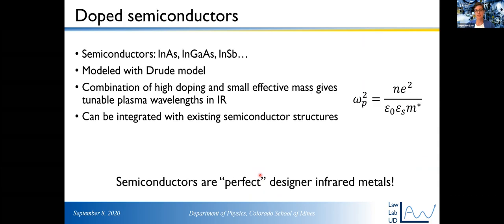So the materials that we're interested in are doped semiconductors, specifically III-V semiconductors, like indium arsenide, indium gallium arsenide, indium antimonide, and so on. These materials are very well described by the Drude model. They're almost perfect Drude materials. And the reason we like them is that they have a combination of a high doping and small effective mass. So this number, the doping density, can be really big, and this number can be really small, right? If you have a large numerator and a small denominator, you get a large plasma frequency. In our case, the plasma frequency is going to be somewhere within the infrared, where there currently are not really great plasmonic materials.